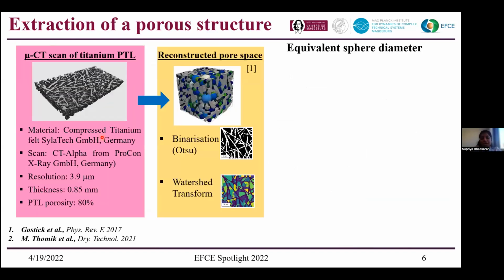Now, before getting into the models, we have to extract the data of this porous structure. So how do we do this? In our group, we are currently working on a commercially available titanium felt, provided by SylaTech GmbH, Germany. We scan this using our in-house X-ray tomography at a resolution of around 3.9 micrometer. This resolution basically depends upon the sample size, and the best resolution that we could get was around 3.9 micrometer. The thickness of the material was around 0.85 mm, and the overall porosity of the material is around 80%.